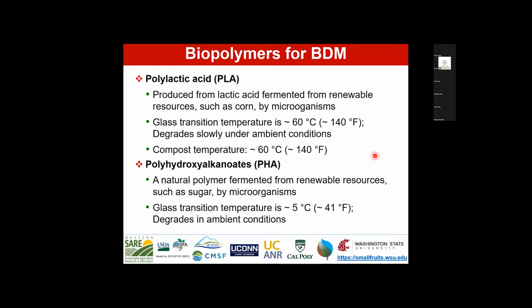Let's revisit the polymers that are used to make biodegradable plastic mulches, or the feedstocks. Dr. Miles provided a really nice introduction. So polylactic acid is one of the biopolymers that are found in some biodegradable plastic mulches. It's produced from lactic acid fermented from renewable resources such as corn by microorganisms. Now, it has a glass transition temperature close to 60 degrees Celsius or 140 degrees Fahrenheit. What that means is that when it's present in natural ambient conditions such as field soils, it is going to be degrading very slowly because it is not able to achieve that glass transition temperature. However, it is able to degrade in composting temperatures because they're able to reach that glass transition temperature of approximately 140 degrees Fahrenheit or 60 degrees Celsius.